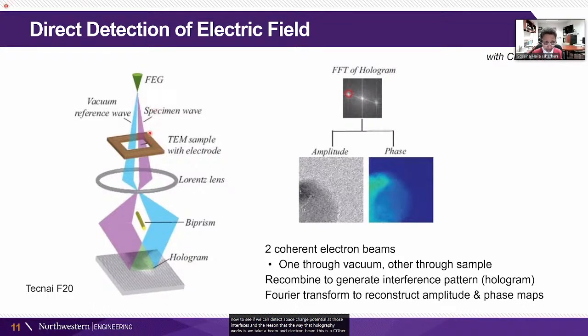This is a coherent electron beam. Split it into two. We have our sample where part of the beam goes through the sample, part of it goes through vacuum. We recombine the two beams using this biprism, and then we generate a hologram. So it's very much like any optical hologram you might have seen. And from this hologram, we do a Fourier transform to reconstruct the amplitude and the phase that was associated with the electron beam coming through the sample.